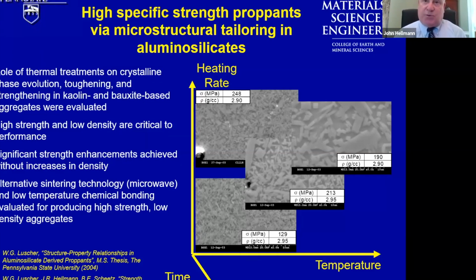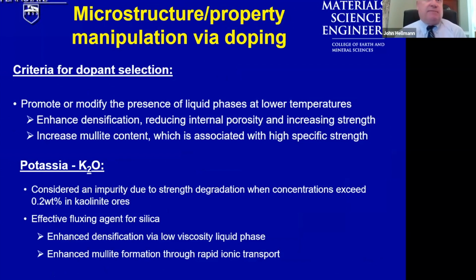Well, in the course of doing this work, we thought, what could we do to improve the sintering process even further, to permit even lower sintering temperatures and perhaps even finer microstructural evolution? And so we embarked upon processes whereby we, recognizing that the materials sinter via a liquid phase sintering mechanism, could decrease the viscosity of the liquid phase during the sintering process, increase ionic transport, and indeed also take advantage of transient liquid phase sintering mechanisms to yield high degrees of densification, appropriate phase evolution, and high strength proppants.